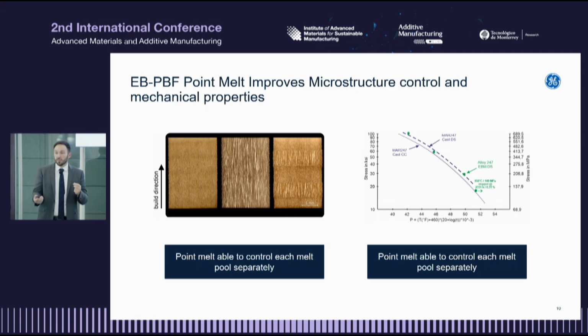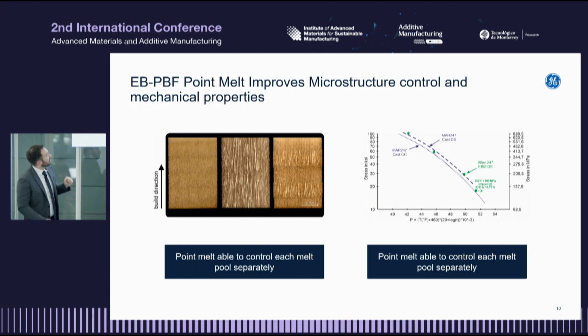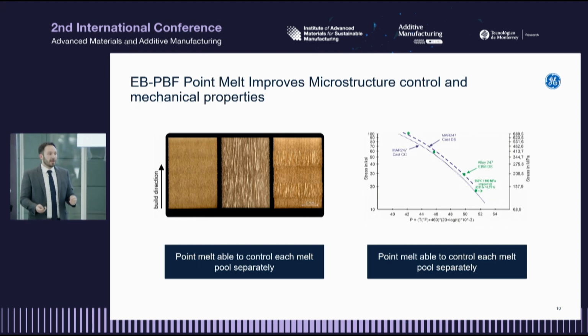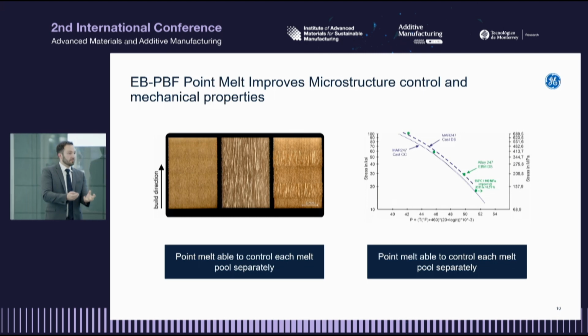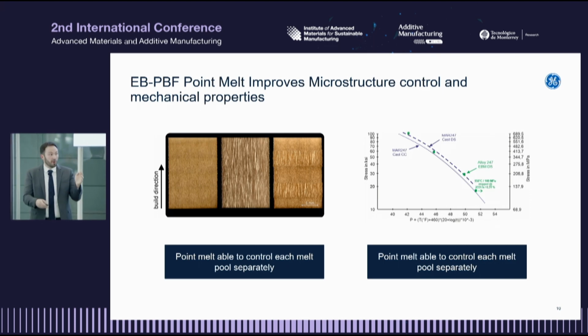By changing how those points behave when they interact with the powder bed, we can create what amounts to a directionally solidified structure. And the one on the right-hand side is a hybrid version of that. If you were in the turbine blade space, I would imagine you would love an equiaxed root, an equiaxed top panel, and the portion of the airfoil that you don't want to creep could be directionally solidified structures. So without even changing the powder, you're just slicing the part with slightly different parameters, you can get this hybrid structure that can be utilized for components.